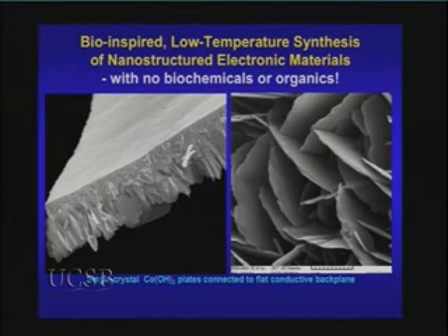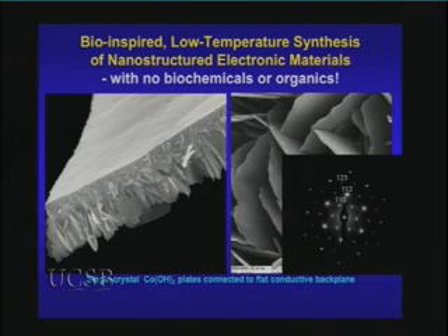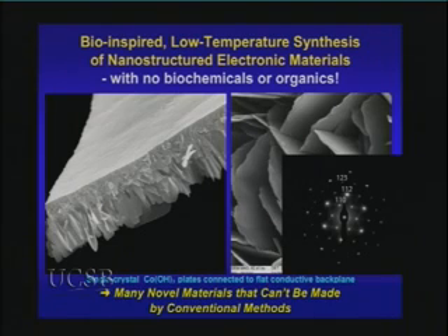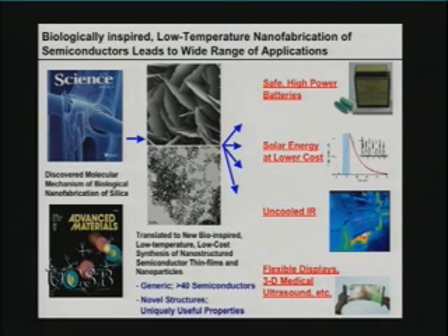And if you look at the resulting material in 3 dimensions, here with a scanning electron microscope, you see that the nanocrystalline material that first started to grow at the meniscus then continues to grow sort of like rock candy, growing into a growth solution of the molecular precursor. And these are highly crystalline nanostructures projecting from the electronically conducting backplane of, in this case, cobalt hydroxide. Electron diffraction shows that these plates are highly crystalline. And in this way, we have found that this is a very generic method. We can make many novel materials that can't be made in such form by conventional high-temperature methods. As a result, we've been able to find novel properties in a number of them.